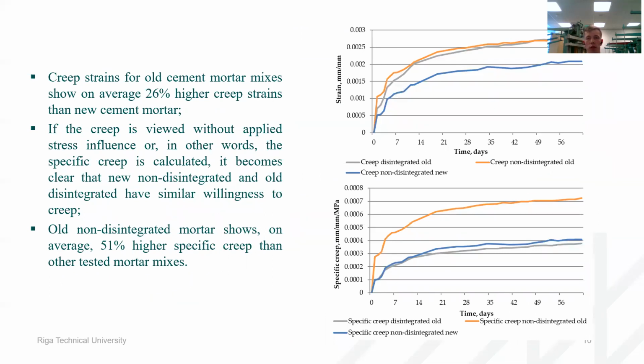If we take from the complete strains out the shrinkage strains, we can see that creep strains for the mortars are almost similar to the complete strains from the creep test, and all disintegrated and non-disintegrated old cement mortars show similar creep strains. As for the creep strains for the new cement mortar, it is 26% less than others. But here we have to take into account that because of the different compressive strength values, the 20% of the compressive strength value that was applied to the creep test stands is different for all the cement mortars. Therefore, all of the compositions are loaded with different load, and therefore subjected to different stresses.